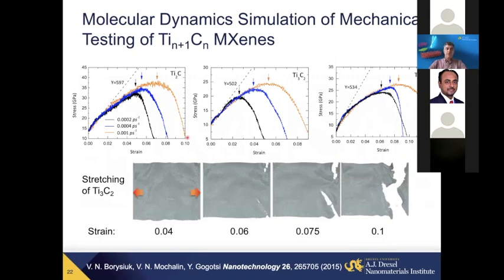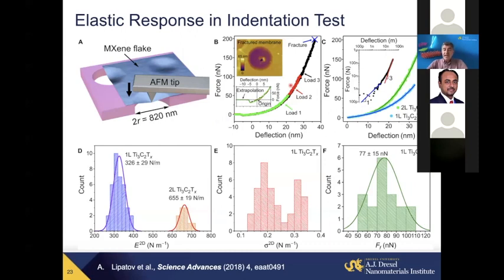A couple of years ago, together with Dr. Vadim Borysyuk from Sumy State University, who was a visiting scientist at Drexel at that time, we conducted molecular dynamics simulation of mechanical properties of MXene, the dynamics of fracture. You can see they can sustain significant strain up to 10% and show very high predicted stress to failure, close to 30 gigapascal, depending on type of MXene and number of layers. And experiments largely confirmed this.